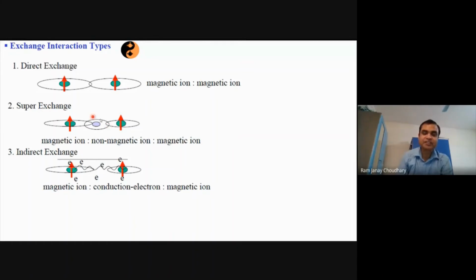In this super exchange interaction, the two magnetic moments which are talking to each other are not directly connected; rather they are far apart, but they are connected by some kind of non-magnetic ions like oxygen. If you take the example of Mn2O3, the two manganese ions are separated by oxygen in between, and those two manganese ions interact with each other by this super exchange mediated by oxygen, right? So the electrons of oxygen and the manganese all hybridize in a way that leads to a kind of super exchange interaction.